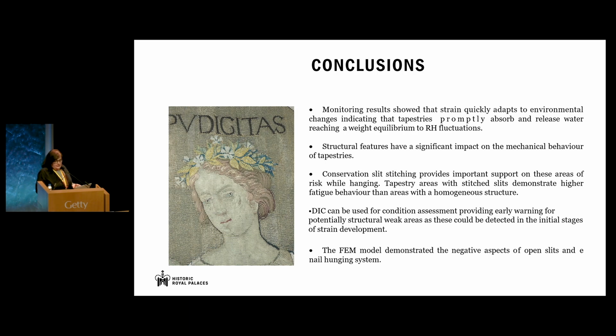Overall, the results suggested that the strain in tapestries adapts closely to the environmental changes, indicating that the fibers quickly absorb and release water. The structural features, such as the weave interruptions and the presence of slits, have a significant impact on the tensile properties of the tapestries. Potentially, DIC can be used in the future as a technique that can identify areas that might suffer from more damage in the future.